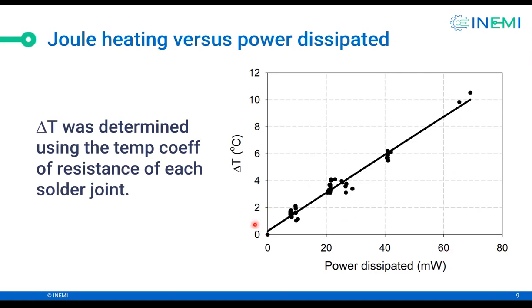I won't go into any details, but what we do is we measure the joule heating for many, many specimens, and we measure the power dissipation. So we get essentially a straight line that goes through almost 0, which it should. And from then on, since we know the power dissipated in a solder joint, we can calculate the joule heating temperature, and we add that to the oven temperature to get the true temperature of the solder joint.